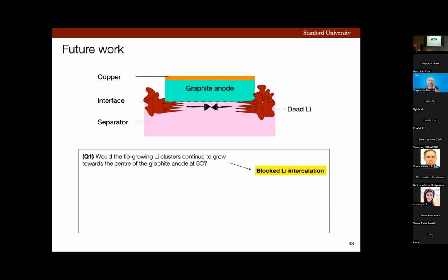Now, in the future, I'm curious to know, would these tip growing structures continue to grow towards the center of the graphite anode at 6C, leading to a completely blocked lithium intercalation? So the battery wouldn't short, but it would have a significantly lost capacity that it wouldn't work, which is a form of battery failure. Or would these tip growing structures fully penetrate the separator at 6C, leading to battery short circuit? Which one of them would happen first, or would they happen concurrently?